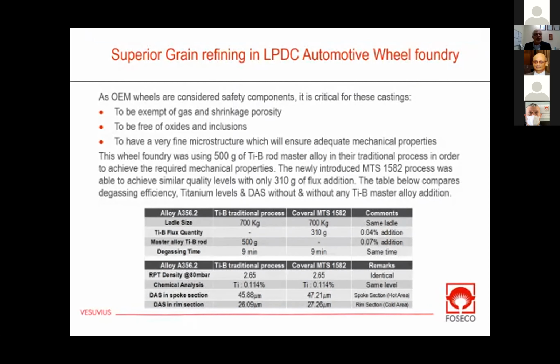In modern OEM wheels, you need a DAS which is smaller than 50 microns. I'm only showing this because, for the wheel foundry, this was a way of checking that the wheels they were making with our new process were within specification. If the DAS had been higher, they would have rejected the wheel and said something is wrong. So the DAS measurement is only a way to check that this wheel is within the foundry's specification.